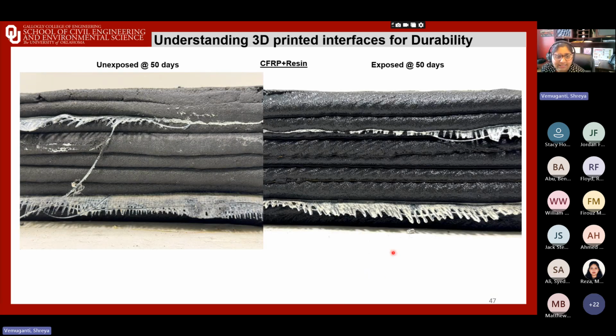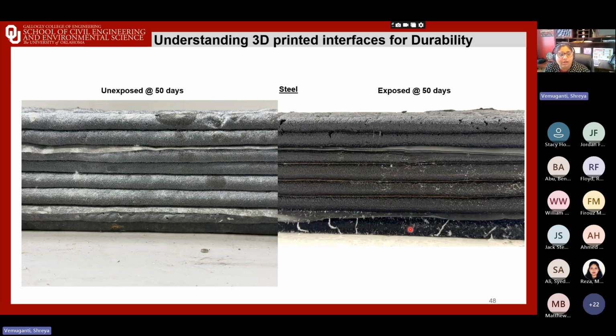In the CFRP plus resin, actually, this was the best looking specimen so far at 50 days. It's an encouraging sign that material selection and surface treatments can be tuned to provide some durability of these printed interfaces. With steel, we saw some sort of decoloration here and staining. Again, we did see some ettringite crystallization as well.